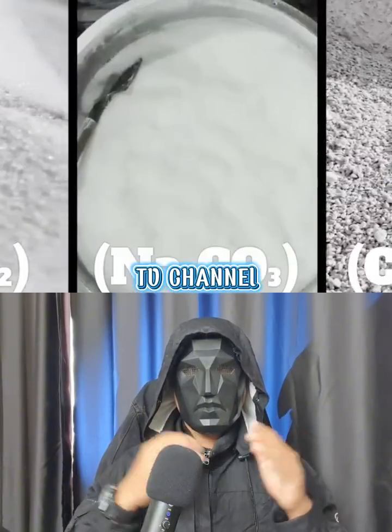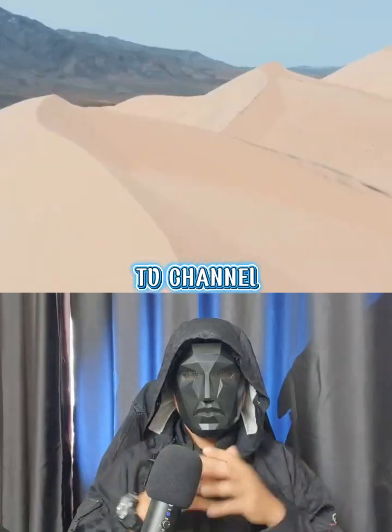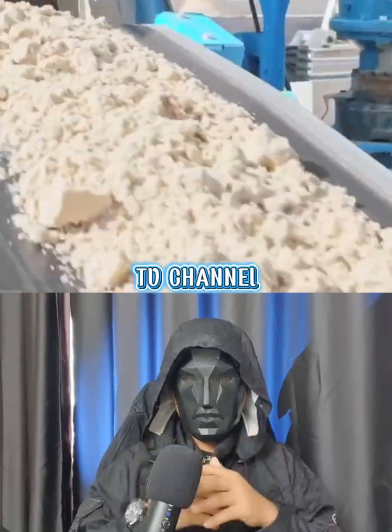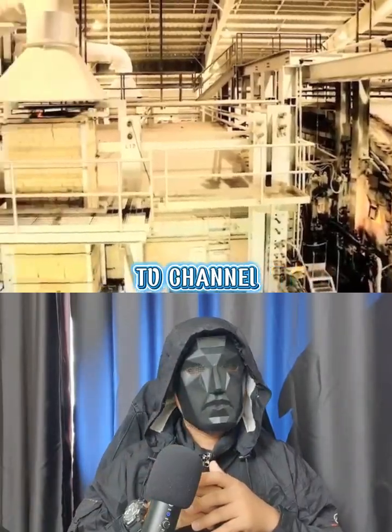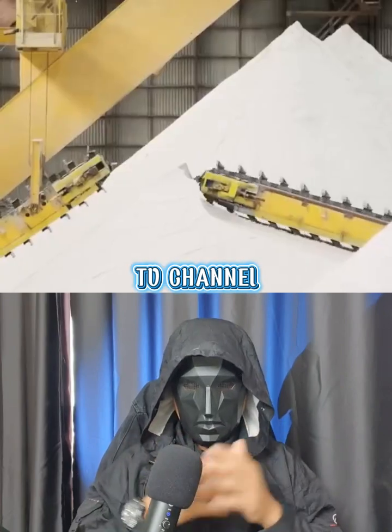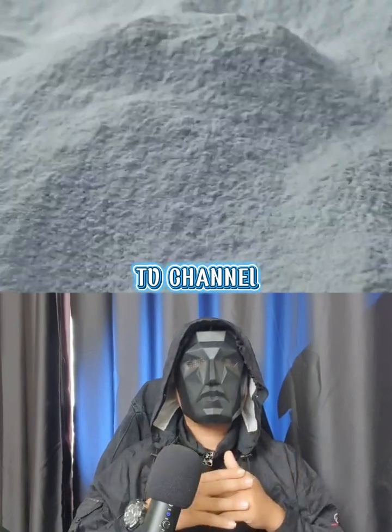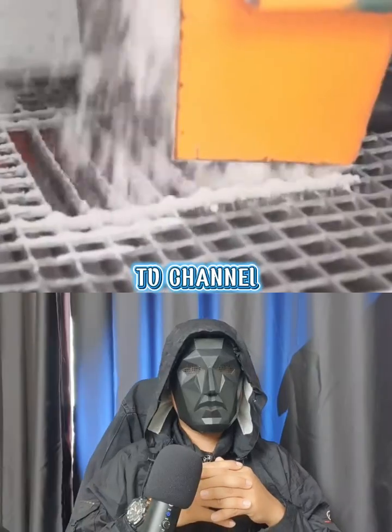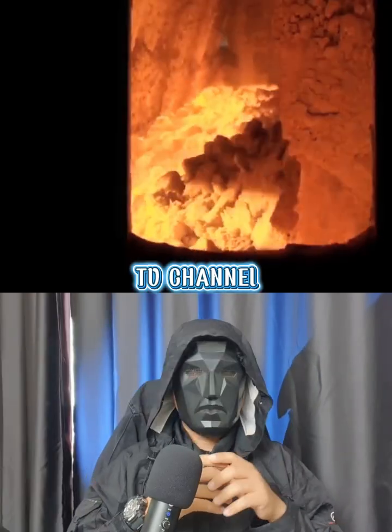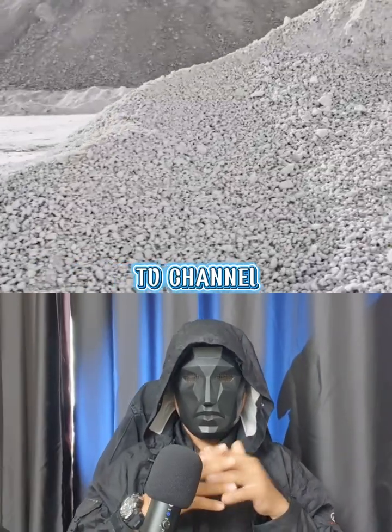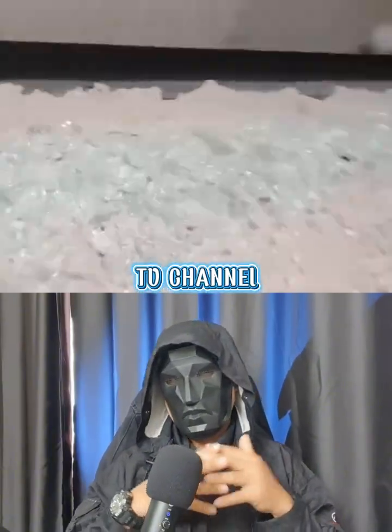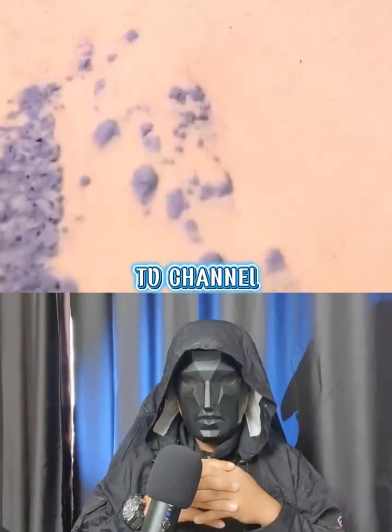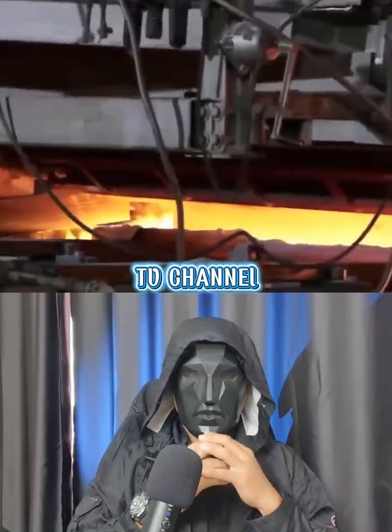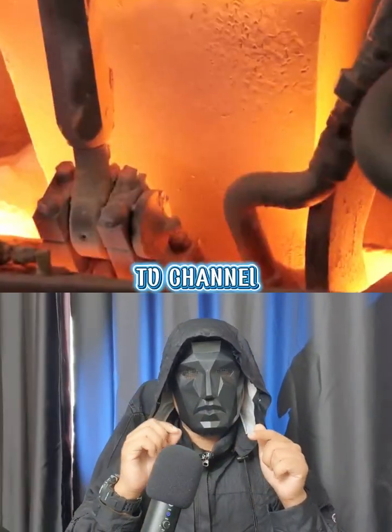glass sheets. The main raw materials are silica sand, about 70 to 75%, soda ash, sodium carbonate, to lower the melting point, limestone and dolomite, calcium and magnesium oxides, to act as stabilizers and improve durability, and cullet, recycled glass, which reduces energy consumption. These materials are precisely weighed, ground into fine particles, and thoroughly mixed in a batch house.